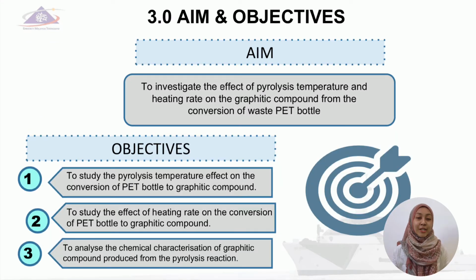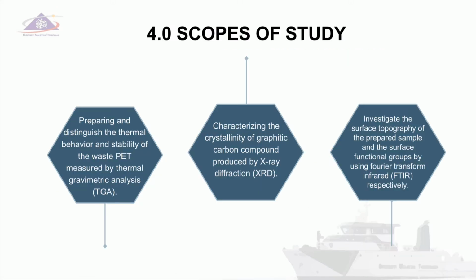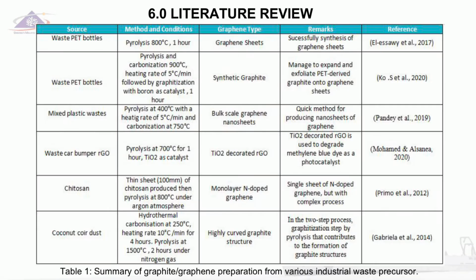So the aim of my study is to investigate the effect of pyrolysis temperature and heating rate on the graphitic compound from the conversion of waste PET bottle. In order to achieve that, my objectives are to study the pyrolysis temperature effect, to study the effect of heating rate, and to analyze the chemical characterization of the graphitic compound produced from the pyrolysis reaction. Most of the studies shown use pyrolysis as their method with additional steps such as carbonization, graphitization, and the addition of catalysts. In my study, direct pyrolysis without any additional steps was attempted.